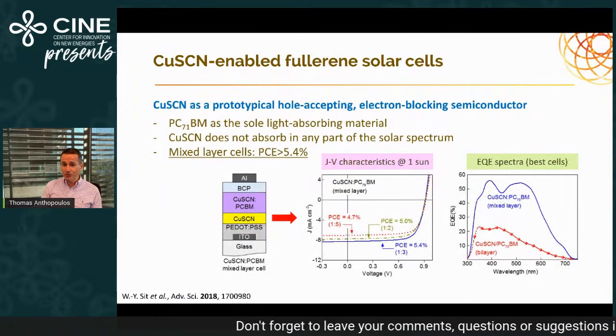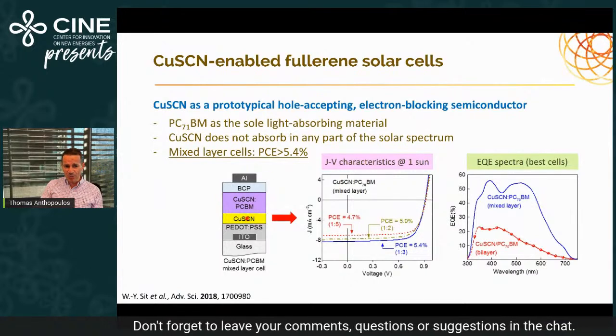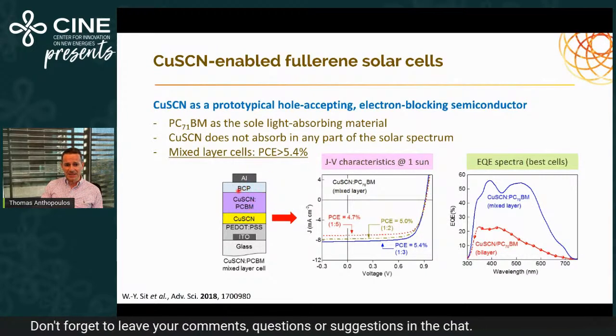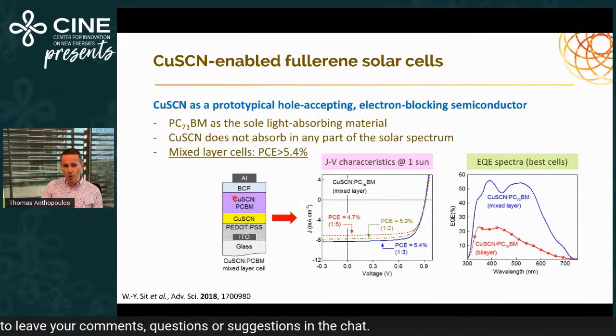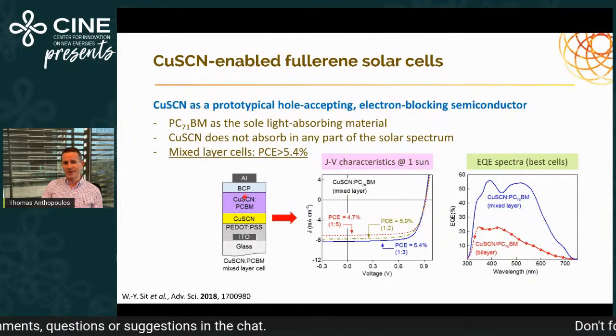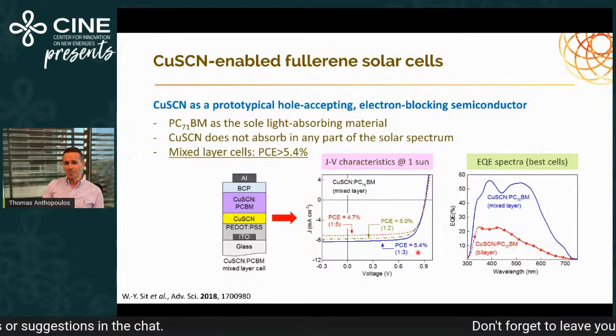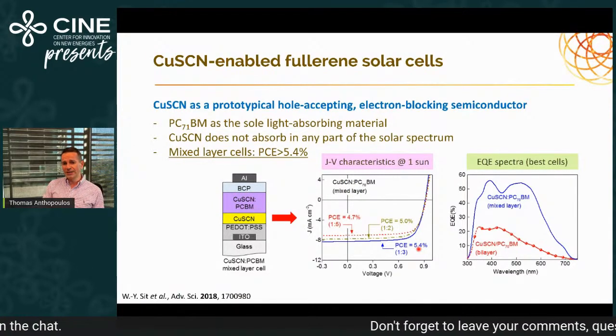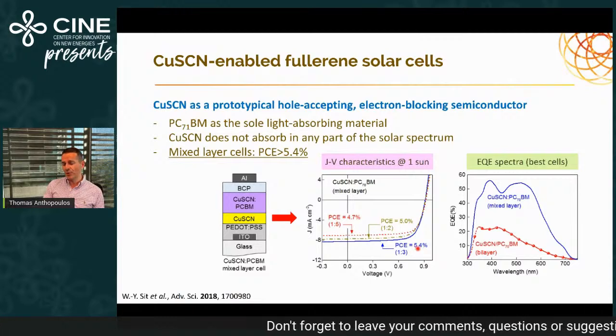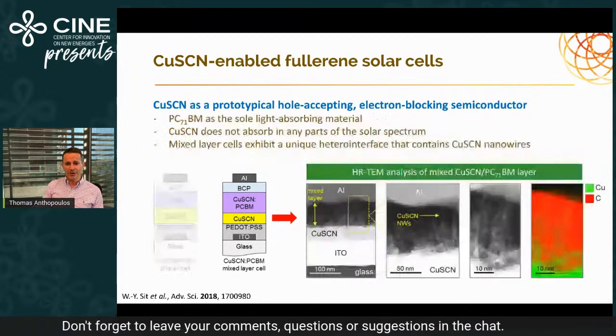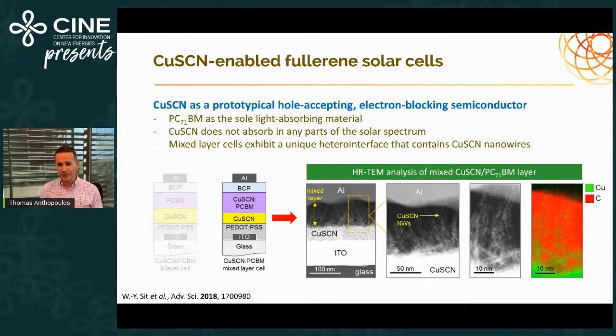We're able to improve it dramatically by taking this copper thiocyanate and the PCBM, but now within the PCBM, we also introduced a small amount of copper thiocyanate. And we're able to make mixed layer devices with a 5.4% power conversion efficiency. Why was it so much higher? Simply because we increased this interfacial area.